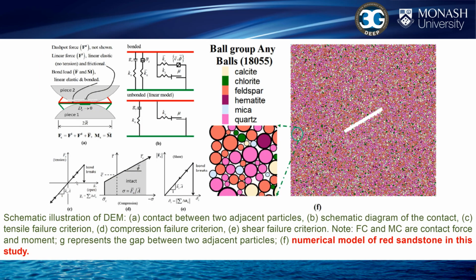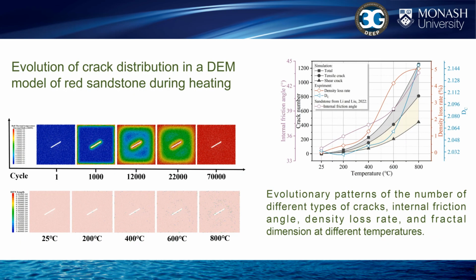We also simulated the evolution of thermal damage development in the specimen using DEM. The number of different types of cracks, internal friction angle, density loss rate, and fractal dimension at different temperatures show evolutionary patterns with similar trends.